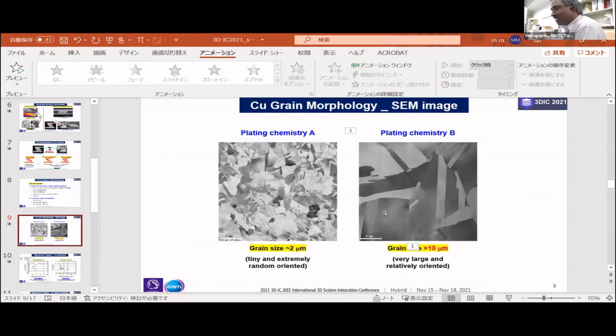Okay, thanks. So these are some of the results. What is shown on the left is a conventionally used plating chemistry, where after copper electroplating your grain size is somewhere around a couple of microns, and again it is randomly oriented. What is shown on the right is our proposed new plating chemistry, where we were able to improve your copper grain to a minimum of 10 micron, ranging from 10 to 20 microns. In addition, we are able to align our copper grains also. We would like to use this kind of copper film or pad for copper-copper bonding, so that we can get very nice single grain bonding between your top and bottom chip.